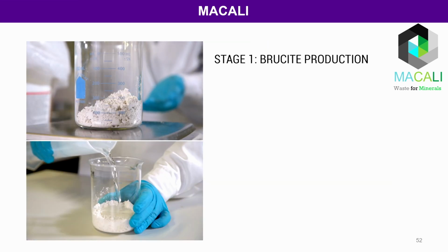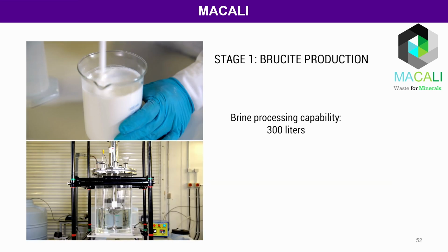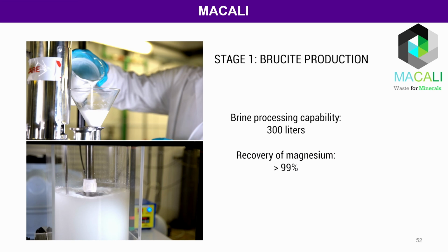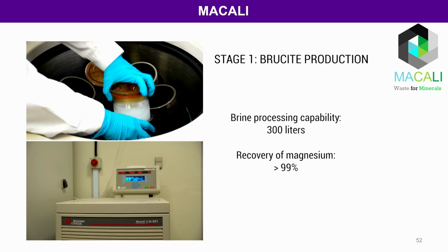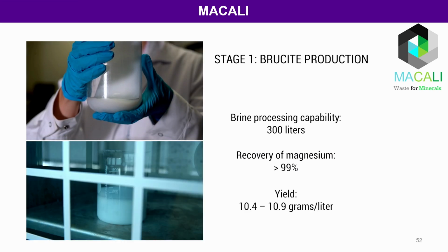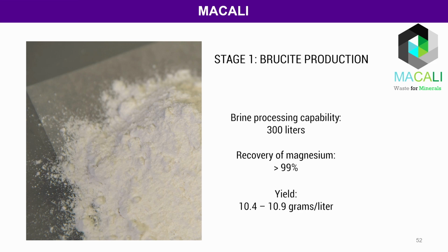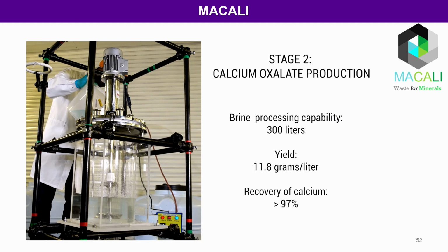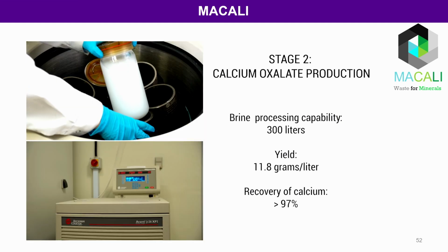The precipitation stages are capable of producing 300 liters of brine per day and recovering up to 99% of magnesium in the form of brucite, with a yield of 10.4 to 10.9 grams per liter. Calcium oxalate can be synthesized with a yield of 11.8 grams per liter.